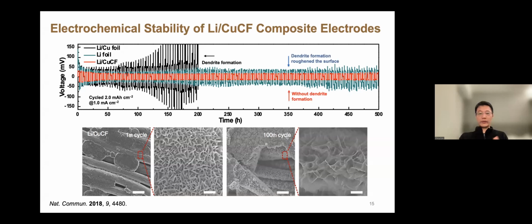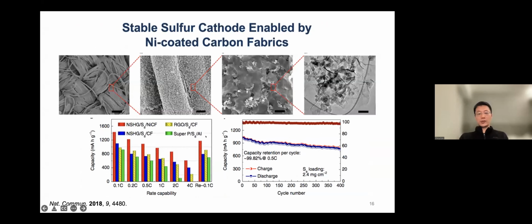We do the same trick on the cathode side, and then you see that again, each of the fiber was coated with a sulfur species, and the result is that we can enable a high rate of redox of the sulfur and also a long-term stability. I'm not going to the detail of the data analysis, but basically the nickel will help a lot in terms of catalyzing the redox reaction.